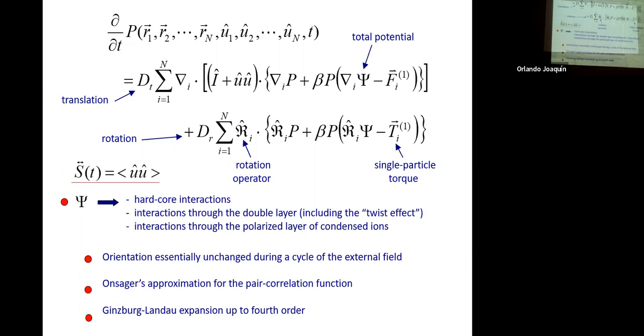And the probability density function has two contributions. There is the change of probability into translational motion, so this is the translational diffusion coefficient. This is the friction coefficient for a rod, which of course depends on whether it moves along the long axis or perpendicular to it. That comes from this term.